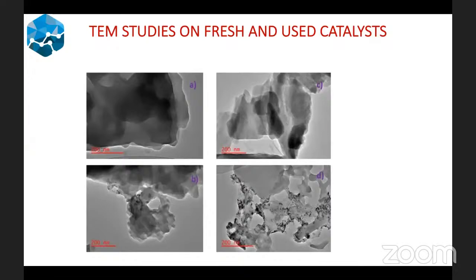We also carried out some XPS studies. Of course, I did not include those results here, which also confirmed that there were some nanoparticles in the used catalyst. The reason why we anchor catalysts on the walls of the MOF is that we want to prevent agglomeration. But of course, during catalysis, nanoparticles may be generated in situ. So I think it's very important to look at all these considerations.